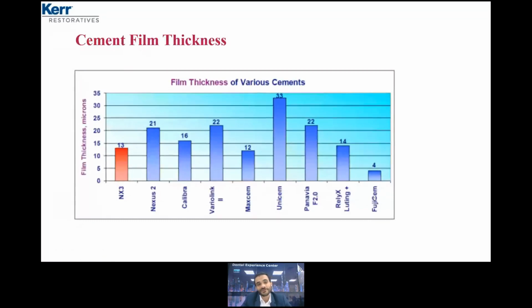It's a glass ionomer, which means, yes, it's very good in film thickness, but the bond strength of glass ionomer, because it's water soluble, will not be equal to the dual cure resin cement. So low film thickness, but not the same bonding strength, equal or similar to the Nexus and the dual cure resin cement.